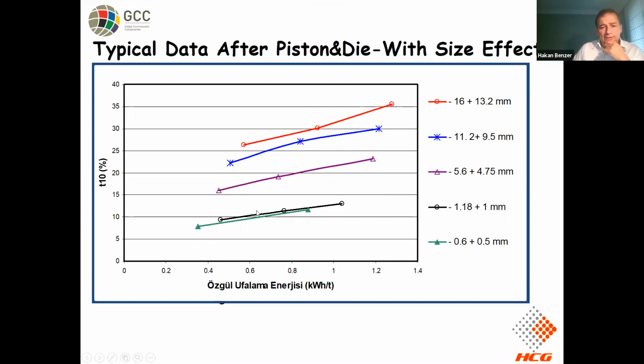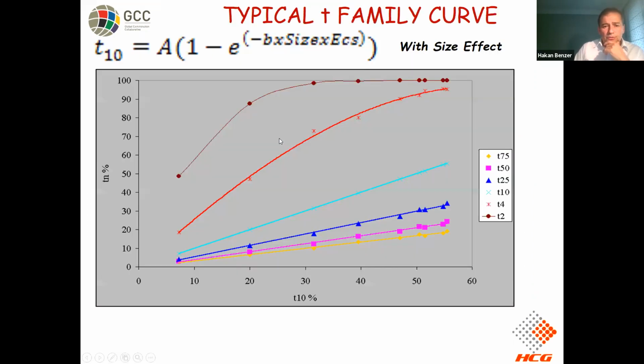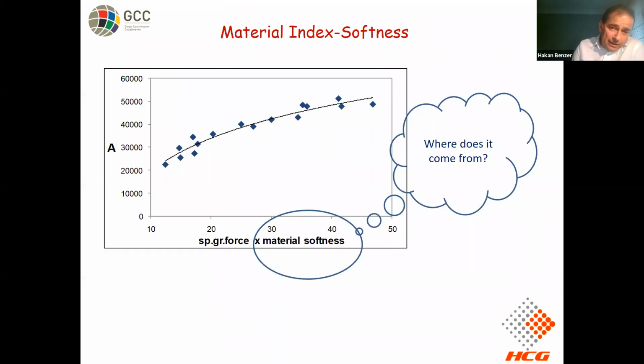You can see the size effect here. So we reflect this effect on the t-family t10 curve by implementing the size effect with varying energy levels. We can define, by using this t-family curve, the breakage rate function and breakage distribution function. But the other parameter which I addressed as material softness or material index, where does it come from?